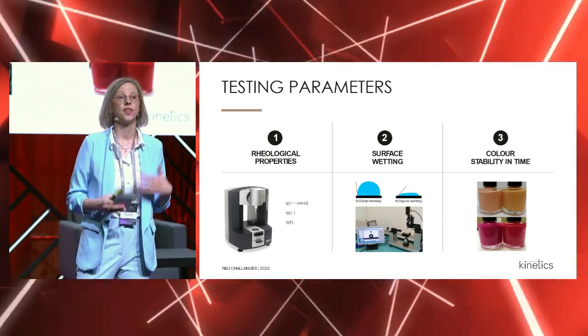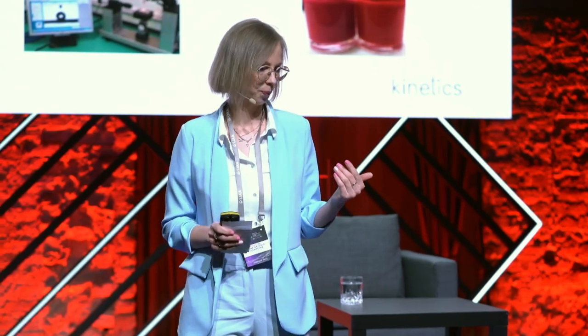The second parameter is surface wetting. I will repeat once again that the natural nail is really a special substrate. It is quite an oily substance. And we need to ensure good wetting on a quite oily substrate. The coating should wet the natural nail, and also the layers of coating should wet each other.